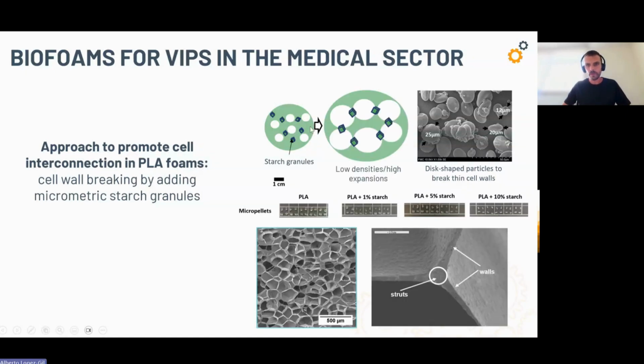If we have these particles in the walls of the foam, when the foam reaches very high expansions, if they are properly placed, these particles in the walls, maybe at very high expansion, maybe we can promote the breaking of the walls. This is the idea. So we have particles that are small initially, so that we promote foam growing. So we don't promote the collapse of the foam. We allow the foam to grow without collapsing.